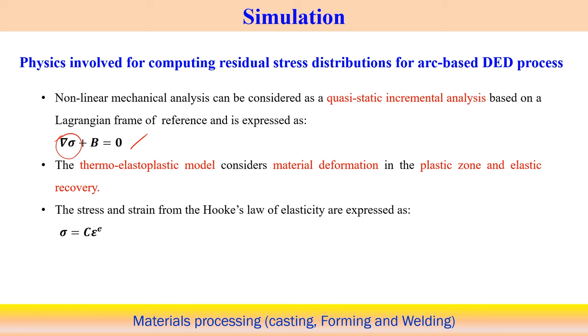Now this internal stress develops when there is an application of load, which can be any kind of mechanical load, or it can be a thermal load to the system for the stress analysis. But in this case the load is in terms of the thermal analysis, the thermal load basically. So temperature differences at the different points induce the strain, and that strain is basically responsible for the generation of the residual stress. But the strain distribution is non-uniform over the space, so that is why it creates the plastic deformation within the domain. And of course the plastic deformation along with the elastic recovery creates some kind of permanent stress within the body, and that can be represented in the form of a residual stress. So that is why we can estimate the residual stress from this stress analysis model.